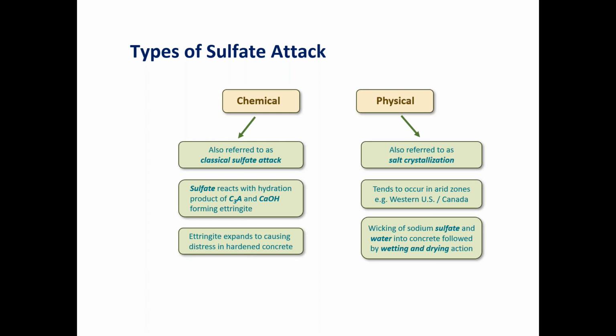It creates volume in concrete, and so over time the concrete is growing in volume, and because of the way we build concrete structures, there's restraint to that expansion. Eventually, if it's a severe enough attack, you start to see these crazy looking cracks form. And then of course from there you have entry points for things like chloride and other nasty things that can also attack the concrete and degrade it as well.